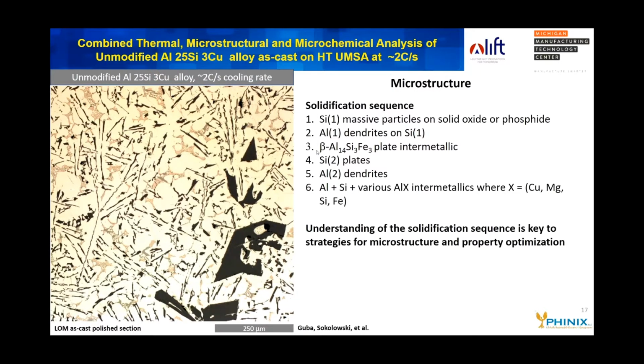Now, they've done work on the aluminum silicon copper alloy, and this is what typical slowly cooled microstructure looks like. First, you get the massive silicon particles. Those massive particles nucleate aluminum on them. So the second phase that shows up is aluminum 1 dendrite nucleating on Si1 particles. Then one actually gets an iron intermetallic to form, which is not visible at this magnification. And then you form a secondary or eutectic silicon plates, which then get covered with secondary dendrites.